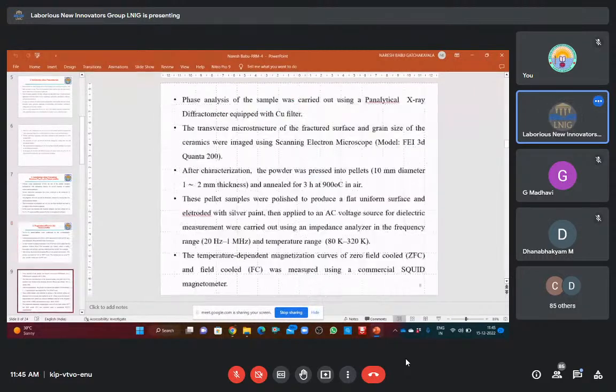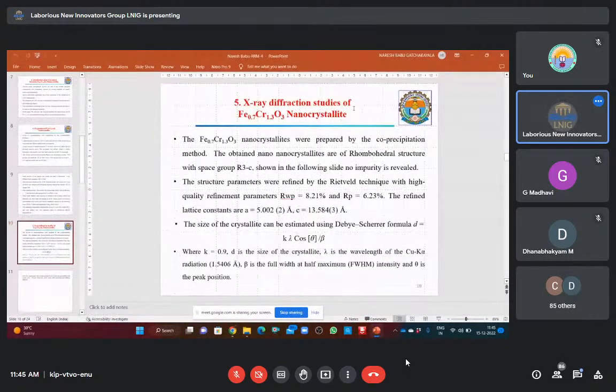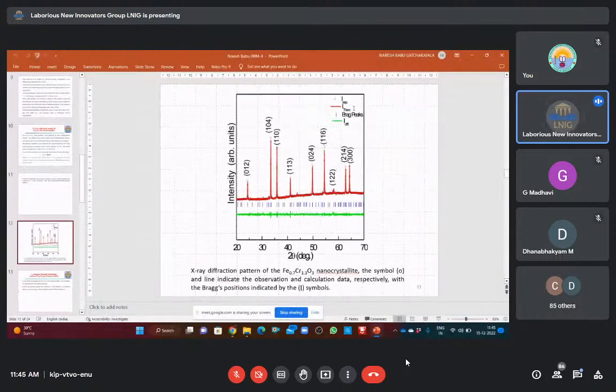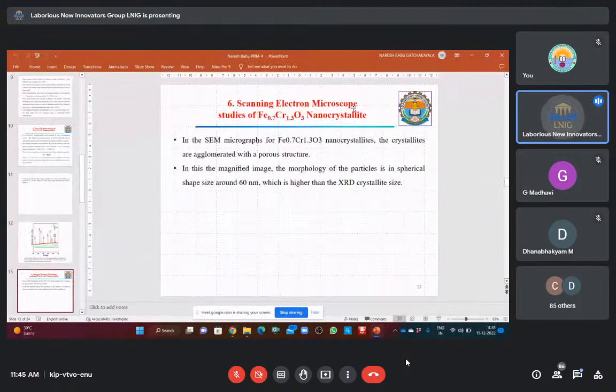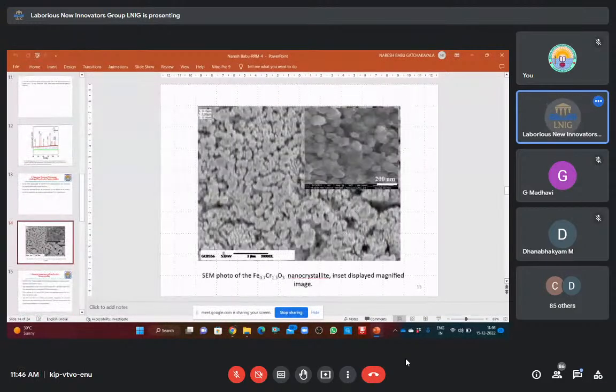Then phase analysis of the sample was carried out using PANalytical X-ray diffraction. So the nanocrystallite I prepared was characterized using X-ray diffraction and scanning electron microscopy. After that, I studied some magnetic properties and some temperature properties. This slide shows the X-ray diffraction studies of that particular nanocrystallite, and this graph represents the X-ray diffraction pattern.